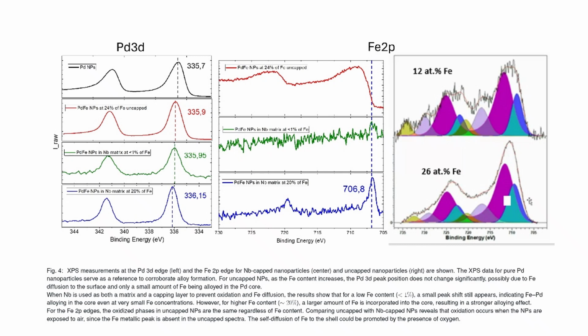For our results and discussion, we characterize the structure of the nanoparticles using high-resolution TEM. In particular, for our sample with 14% of iron content, we measured a mean diameter of 4.1 nanometers, and the images suggest a palladium-rich core surrounded by a shell of iron, which is consistent with the core shell structure. We then perform XPS measurements at the palladium 3d and iron 2p edges.